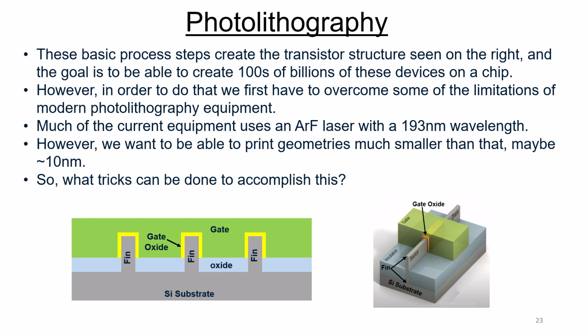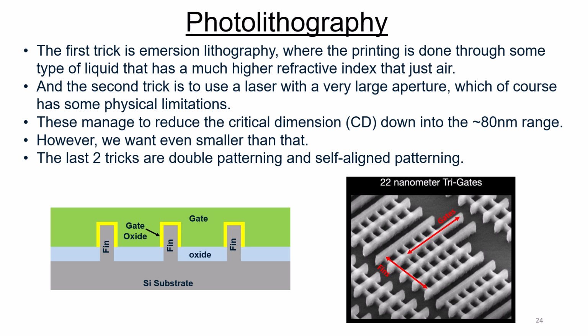Maybe 10 nanometers, maybe even smaller than 10 nanometers. So what tricks can be done to accomplish this? Well, the first trick is immersion lithography, where the printing is done through some type of liquid that has a much higher refractive index than just air. And the second trick is to use a laser with a very large aperture, which of course has some physical limitations. These manage to reduce the critical dimensions, or CDs, down to something in the maybe 80 nanometer range.